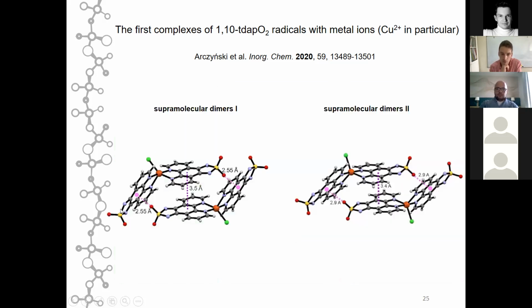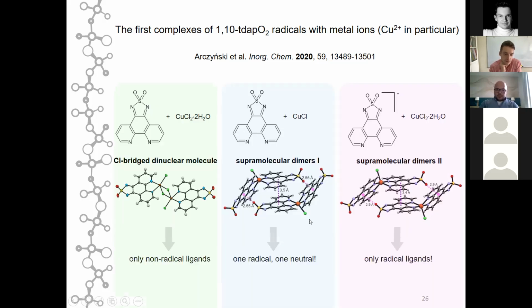Here is a better view of this structure. So some of the ligands actually control the pi-pi stack interactions. The other ones are involved in sigma hole interactions. So I can already tell you that here all the ligands are non-radical, they are neutral. Here there is one radical, one neutral molecule per copper, and here all the ligands are actually in the radical anion state.